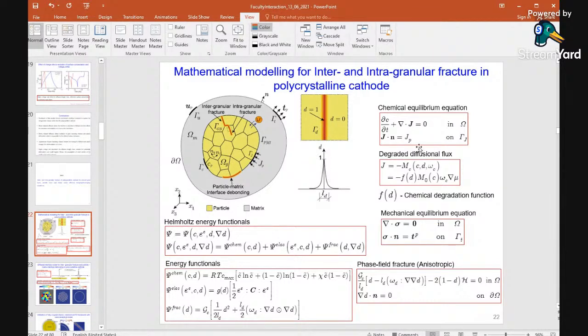So once there is a crack, what will happen? It will stop the diffusion of the ion. So we connect this mechanical damage with the mobility, because that will stop the transport. This crack is developed with one of the pioneer models, the phase field fracture. We have considered anisotropic phase field fracture, and we supplement the previously developed model with this phase field fracture model.